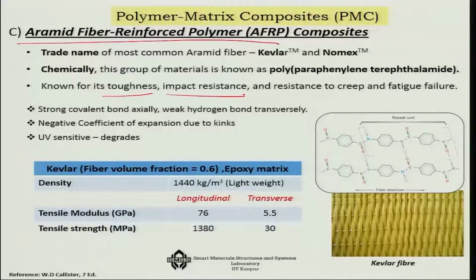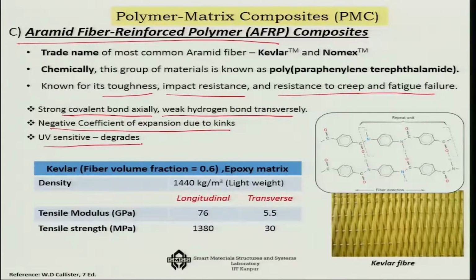This is very much known for its toughness, impact resistance, and resistance to creep and fatigue failure. The reason for its high strength is the axial covalent bonds, however it is very anisotropic. It has weak hydrogen bonds in the transverse direction, and it has a negative coefficient of expansion due to kinks. That is another interesting point you have to keep in mind while designing, and it is UV sensitive. That is a little bit of a negative side of it, that it degrades in UV exposure.